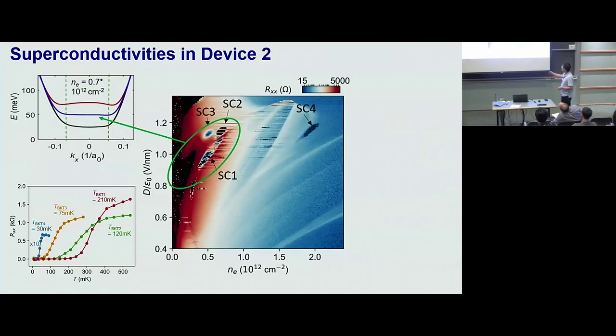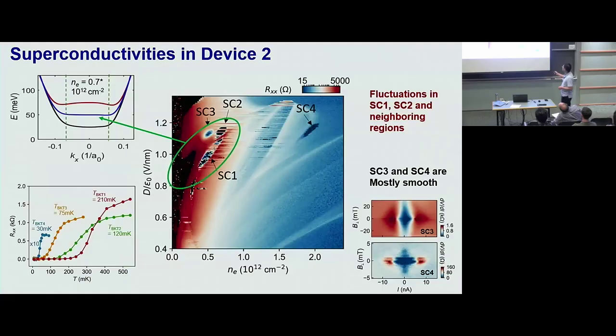Okay, and now let's look at the SC3 and SC4 first. We apply some out-of-plane magnetic field, and you can see SC3 and SC4 can be easily killed by a few millitesla or like tens of millitesla. And this is very typical for graphene superconductivity. It's very weak, TC is very low. With the out-of-plane magnetic field at this level, you can easily kill them. However, this doesn't answer what SC1 and SC2 are, right?